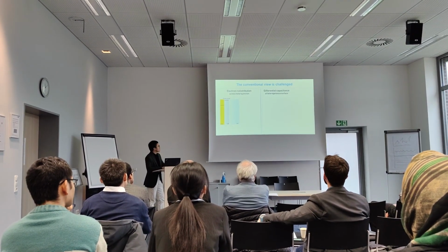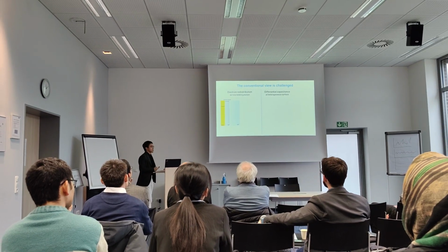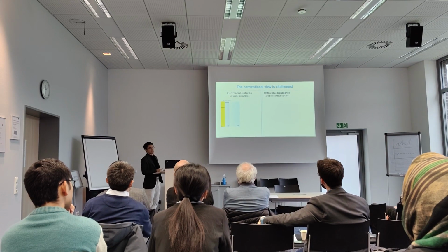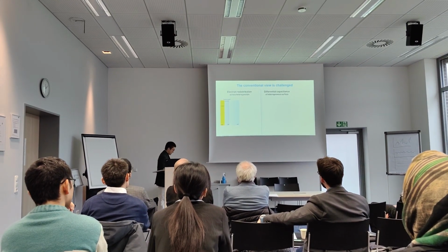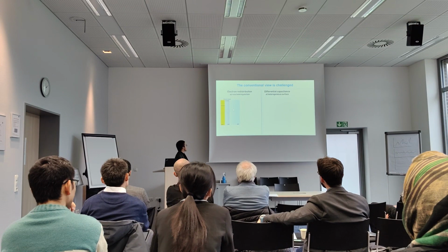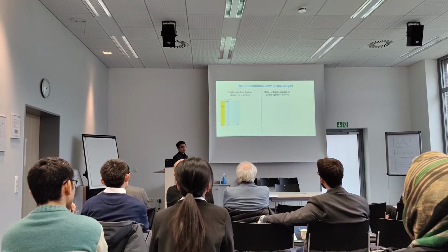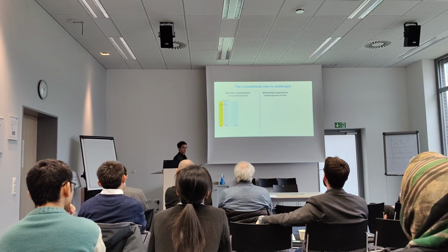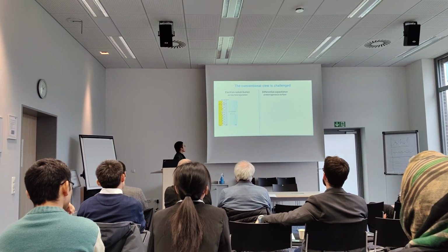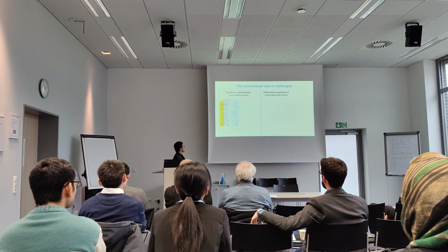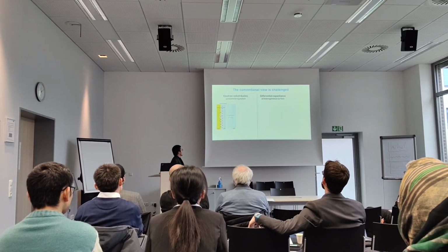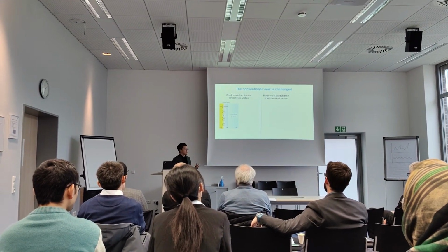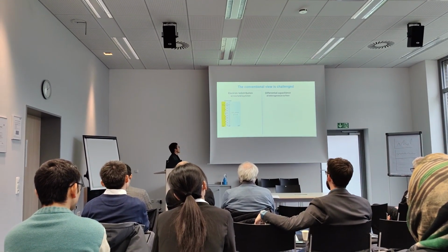So this is what we discovered. Some results challenge the conventional view in two aspects. In terms of electron redistribution, if a catalyst overlayer is on a support, we know there are two different Fermi levels, so electron redistribution will occur, and there is a strong electric field at this interface, pointing from the positive charge to the negative charge. Because metal is a very good conductor, the screening is very strong, so the electric field is nothing in solution.